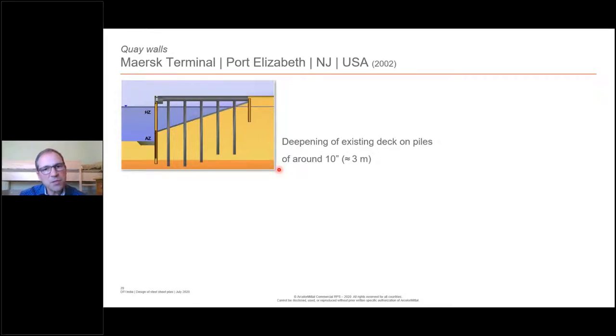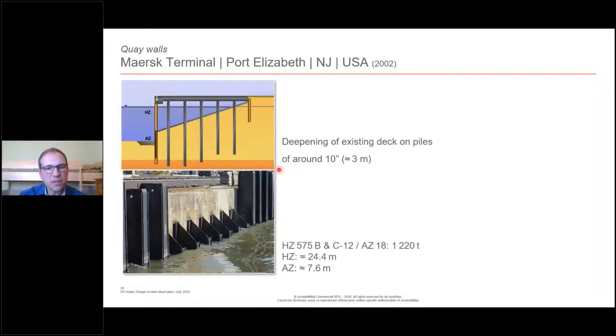Another interesting feature with the sheet piles and the combined wall system is that you can deepen an existing deck on piles, like you see here, where they wanted to increase the depth by about 10 feet, so approximately 3 meters. And the solution that they found is to drive a king pile in front of it with the infill sheets that are shorter, just to secure the slope. And then the king piles were cut at the right elevation, fixed to the concrete deck, and that was it.